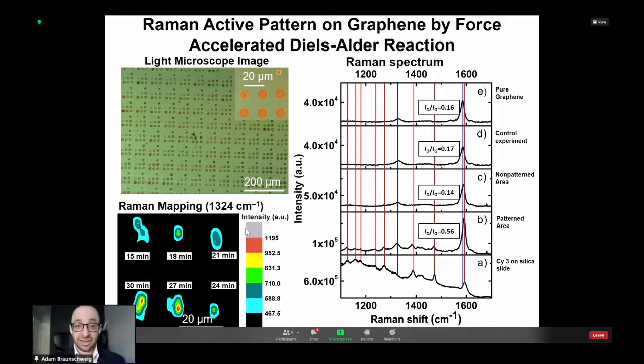And what you see, this is Raman mapping. I think this is the D band, confirming that we get a conversion from sp2 hybridized carbon to sp3 hybridized carbon. That's also what these data show as well. So what you have here is clean graphene, and there's going to be some ratio between the D and the G bands. In our control experiment, what we did was we pushed down on regions of the surface, but in the absence of our diene. So no reaction would occur, and the ratio stays the same. The bonds do not change.